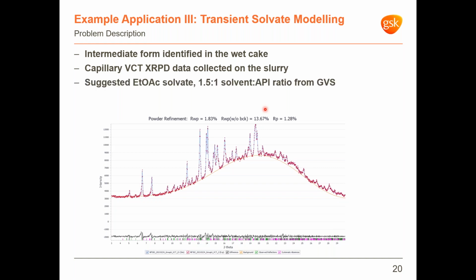GVS, using the dry API development form as input, was suggesting a 1.5 to 1 solvent to API ratio involving the process solvent, that is ethyl acetate. And from indexing of the XRPD pattern, we could link this intermediate to a previously known methyl THF solvate, the structure of which was previously determined by single crystal XRD.